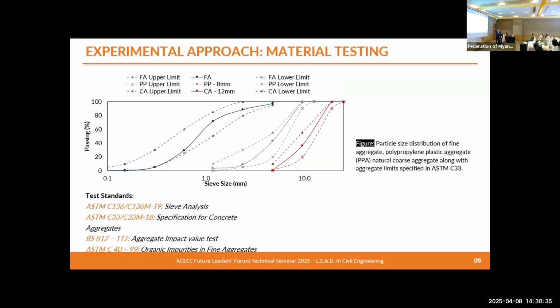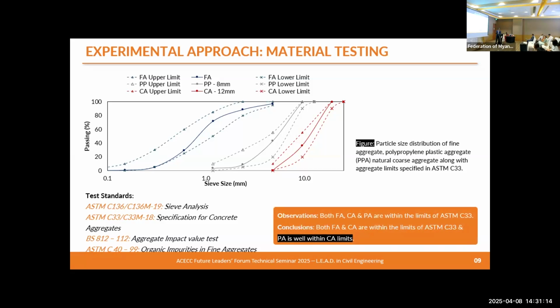This is the sieve analysis results for our fine aggregate, the plastic aggregate, and the natural coarse aggregate. Of the two graphs on the right, in the middle one you can clearly see that it's well within the ASTM limit for coarse aggregate, which implies that we can replace our natural coarse aggregate with this plastic aggregate. But you can see there's a size difference between the nominal size of the plastic aggregate and the coarse aggregate, which gave some negative impacts on concrete workability, which I will discuss later. So with that, we can go with our hypothesis: we can replace our natural aggregate with the plastic aggregate.